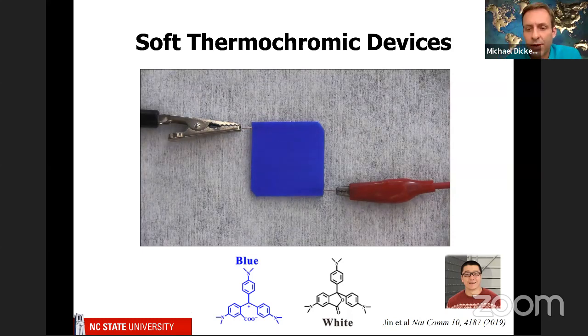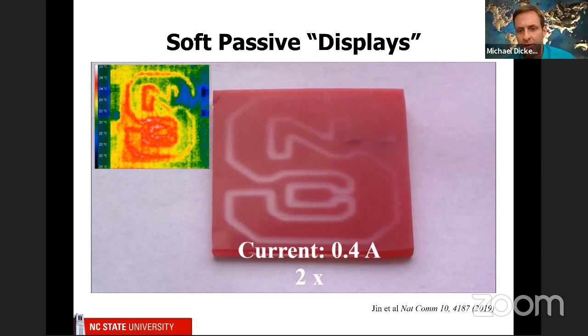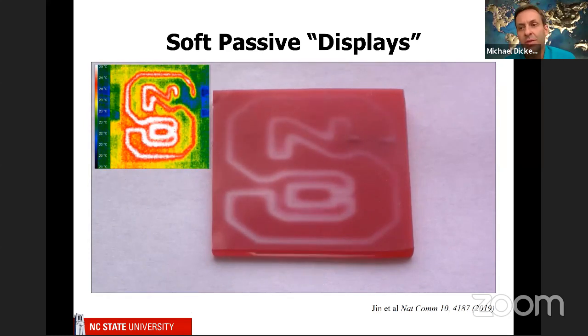And so this is really not surprising, I would say. These are just commercial pigments and we've simply mixed them into the silicone. And you can pattern the liquid metal to create patterns. Basically, it's thermal patterns, which you can see visually because these pigments change color. So again, not too surprising. It looks beautiful, but not surprising.